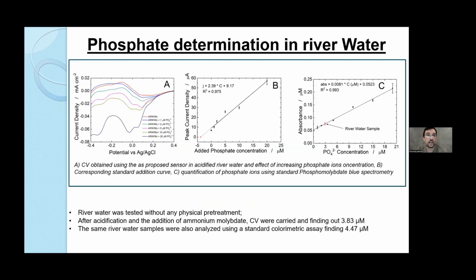So then we have collected a real water sample, a river water from Palermo, and it was tested without any physical pretreatment. Then the standard addition method was carried out after its acidification and addition of ammonium molybdate. And using our sensor, we found a concentration of 3.8 micromolar of phosphate ions in this water.